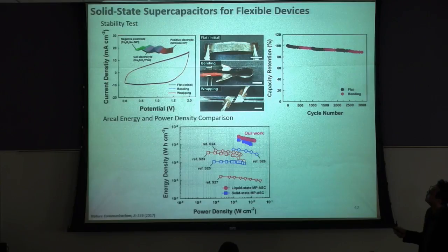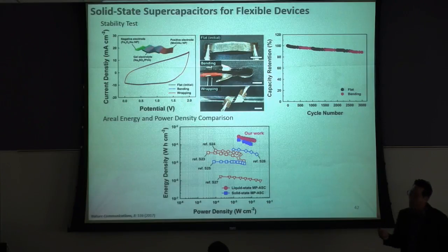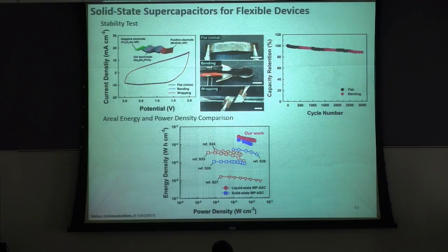So we fabricated the full device. Basically, this is the manganese oxide-based positive electrode, and this is the iron oxide-based negative electrode. We use a polymer-type gel electrolyte. We made a package with PDMS. We do tests under bending and twisting, showing stable performance. Also, we perform cycling stability tests under flat and bending conditions, showing really good cycling performance. When we compare the energy density and power density based on the unit area of this device, it shows pretty high power and energy density compared to previously reported flexible supercapacitors. Also we can simply increase this energy and power by incorporating more active materials.